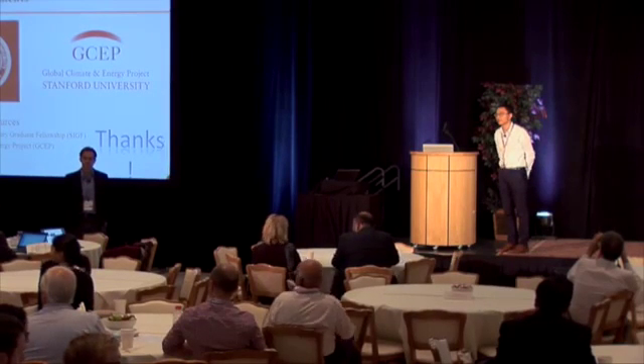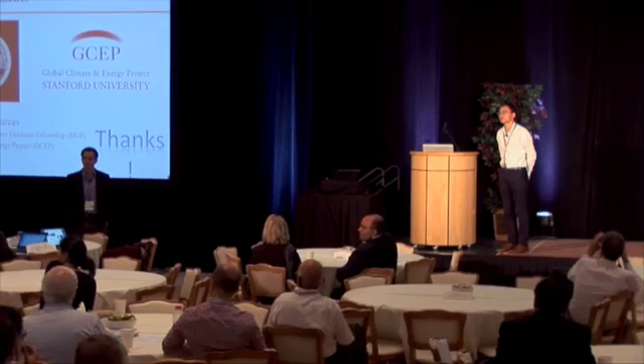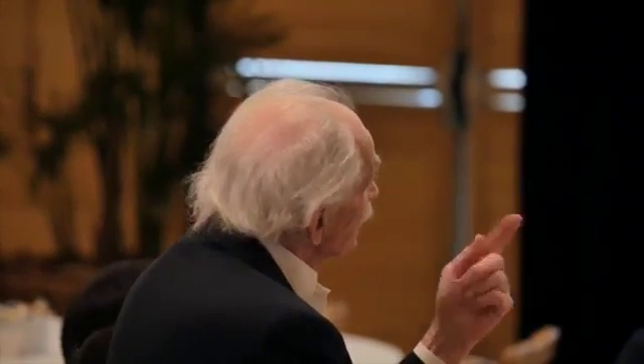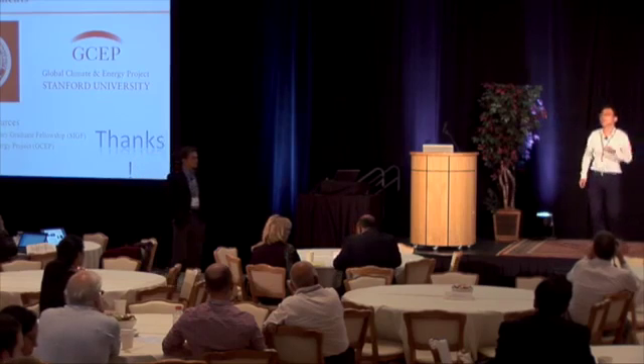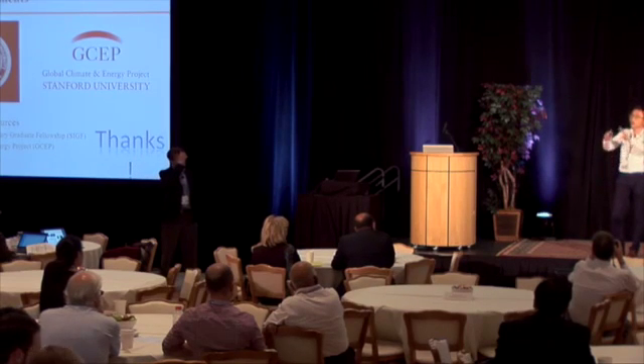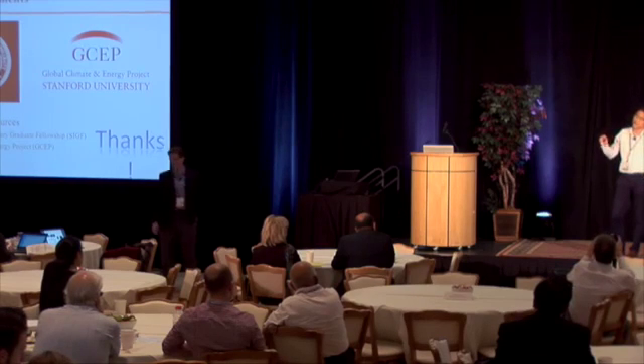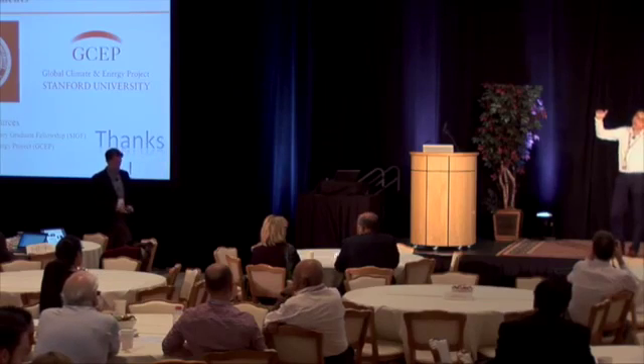So in electrocatalysis, it's mostly the surface that's important, unless you have a very porous film or something. And so although people like to correlate bulk properties with things, it's really the surface that makes all the difference. So if you're intercalating lithium, that's more of a bulk property change. Is it the electronic effect that affects the surface that you think makes it a better catalyst, or what's your feeling? So yes, as you can see, when you intercalate lithium inside, the electronic structure of the whole system is actually changed. You drive a lot of electrons. You raise the Fermi level, the chemical potential, of molybdenum disulfide, for example. It actually has a phase transition from the semiconducting phase to a metallic phase. So the whole system is changed. The surface is changed. The bulk material is also changed.